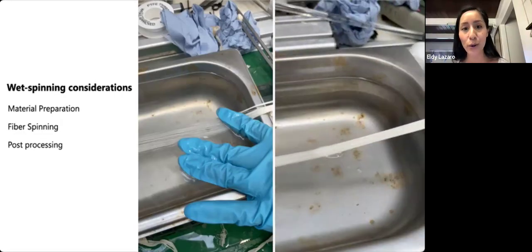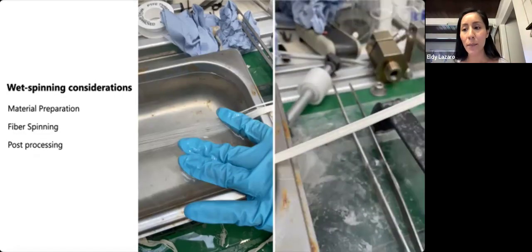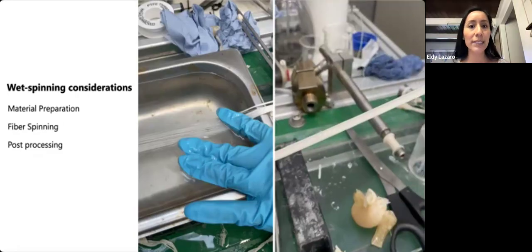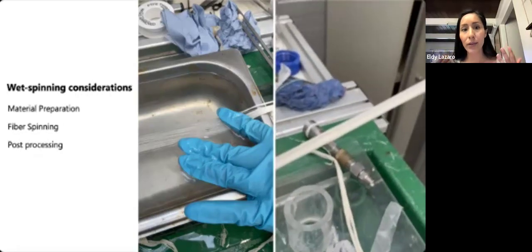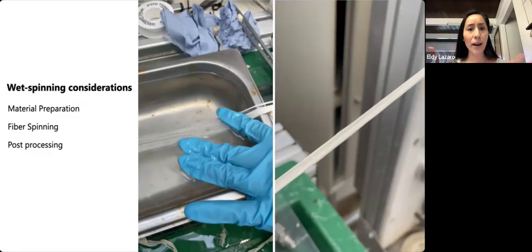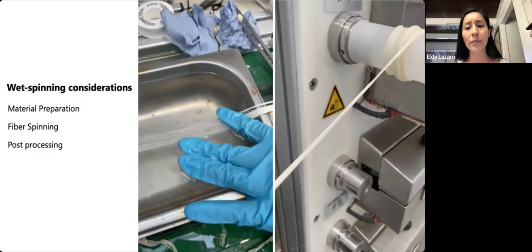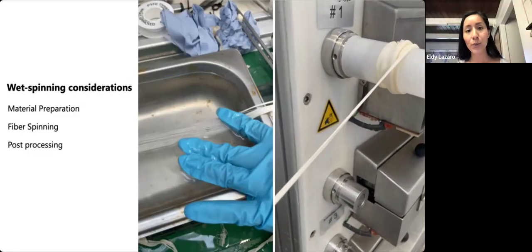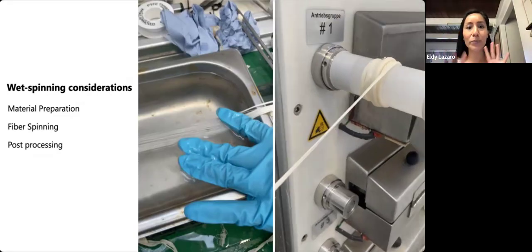The fabrication workflow has been standardized mainly for homogeneous and synthetic materials like polyester or even carbon fibers, but not for biomaterials. So I had to really hack the machine, all the parts, so that I can keep the same temperature at the moment of extrusion. The video that you see here just happened in the last 2 days of my summer there.